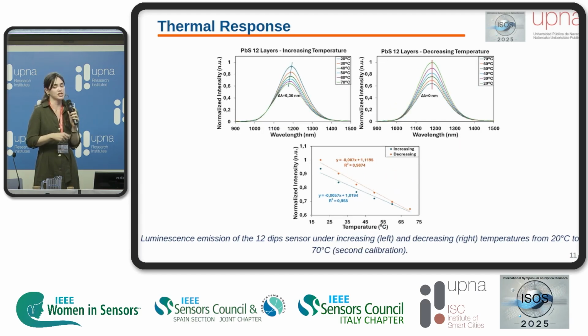After these calibrations, we repeat calibrations for the sensor with 12 dips, and in this case, we obtain similar results, similar values of sensitivity, and linearity. Here we can observe a hysteresis between the cycles, the temperature increasing cycles and the decreasing temperature cycles, but this could be explained by the expansion and contraction of the crystalline network of the quantum dots, which are not identical and not entirely reversible. This behavior is observed in all the sensors.